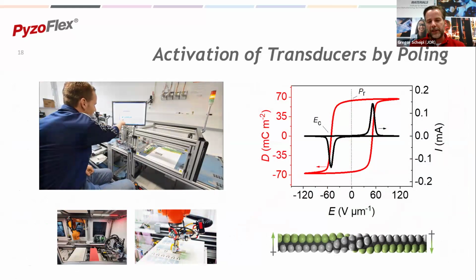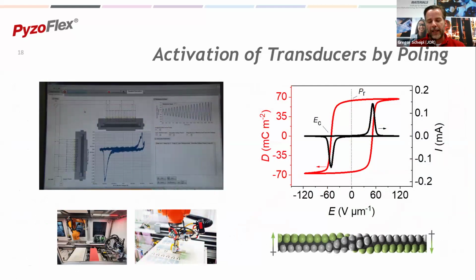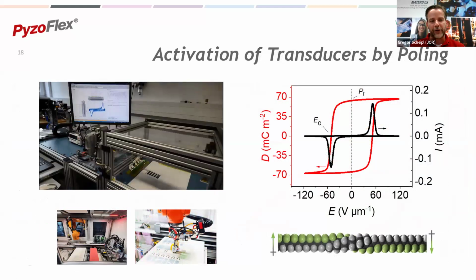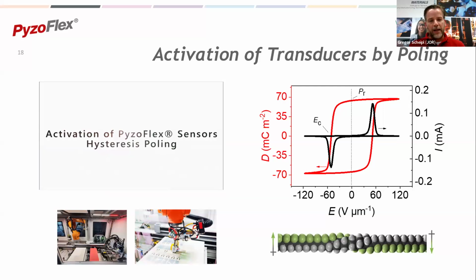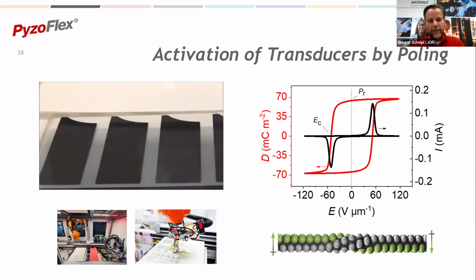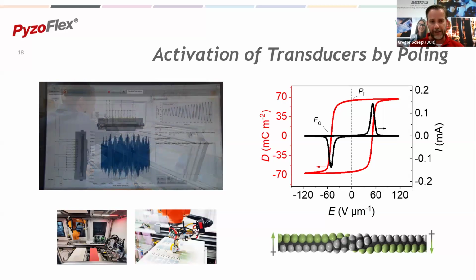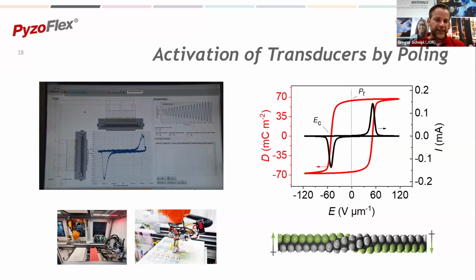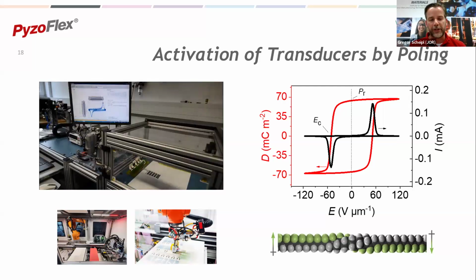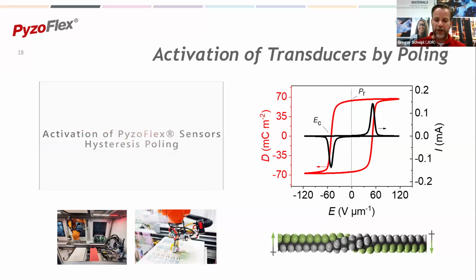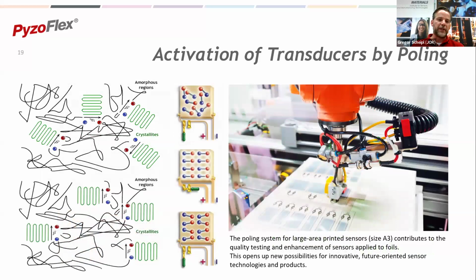It's then also shown in the next slide that this printing material has some dipoles, and after printing they are randomly distributed. And by applying an electric field, you can use different ways of poling. It's like contact poling, hysteresis poling, or corona poling. You insert the voltage in the electrodes. You create an electric field, and within this electric field, the dipoles are perfectly aligned in order to activate the sensor. So here you can see in the video, you increase the electric field, and by increasing this field, you give these dipoles the preferred orientation in order to make them ready for sensing or to detect these temperature, pressure changes or vibrations, which is shown on the left picture here.